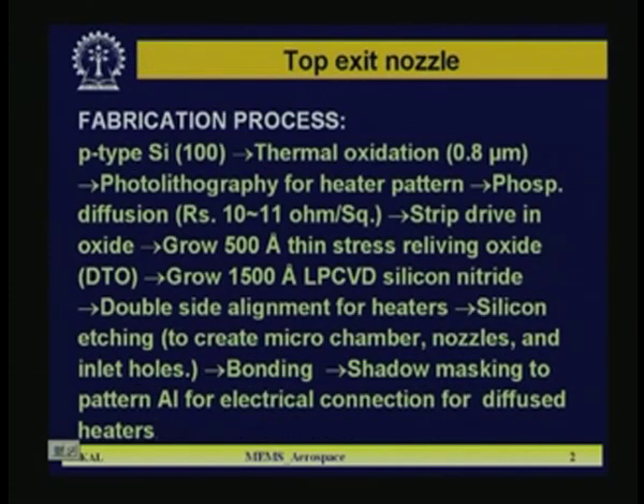Now, what is the fabrication procedure? Bottom was the glass and top was the silicon on which you are making nozzles, chambers, etc. So, they started with p-type silicon 100 and then thermal oxidation, which is 0.8 micron, then photolithography for heater pattern. First you have to go for the design and fabrication of the heater, which is an embedded heater.